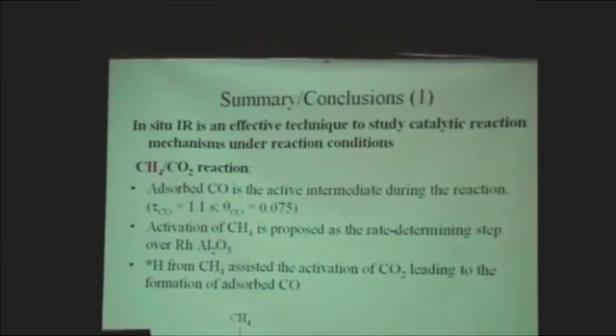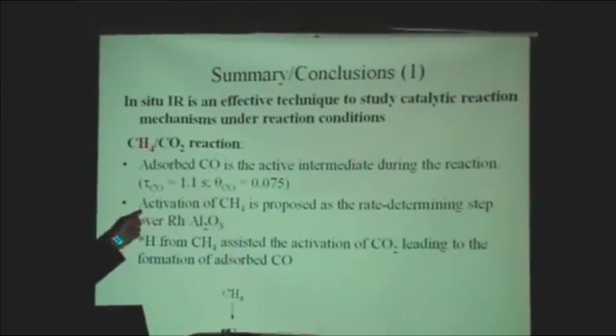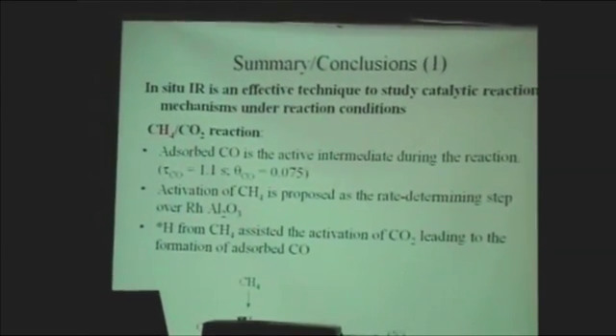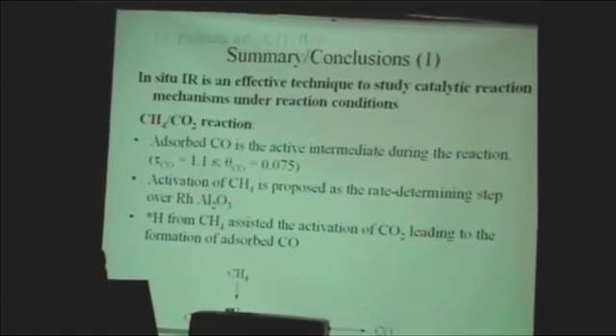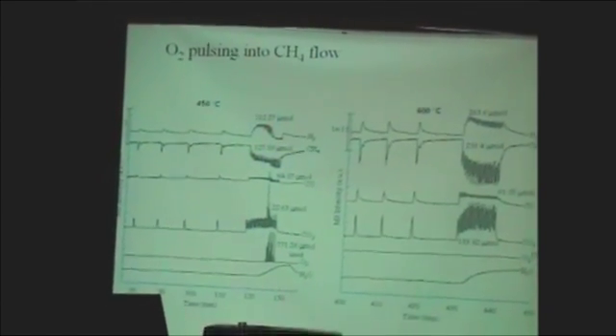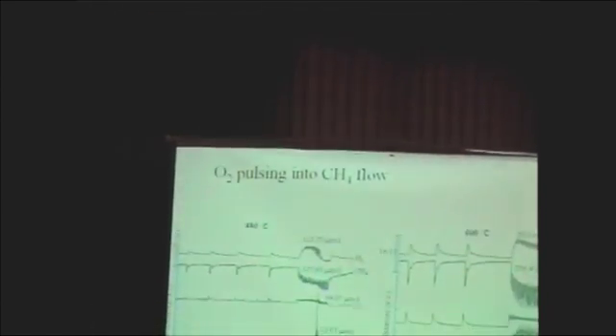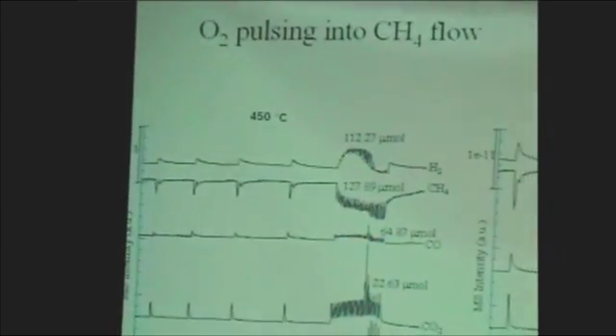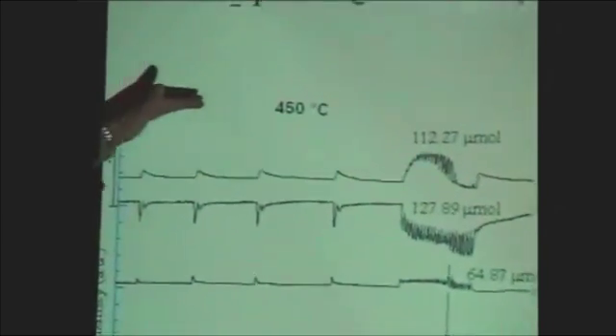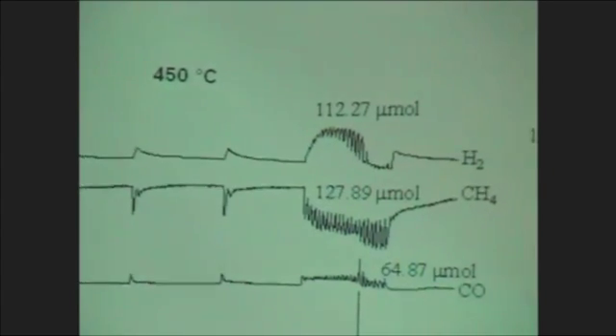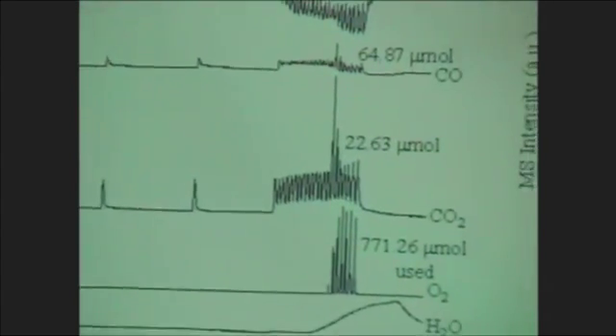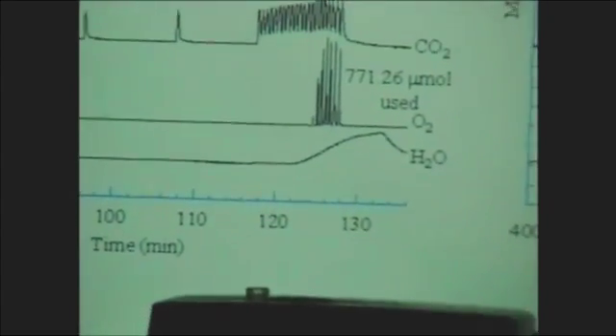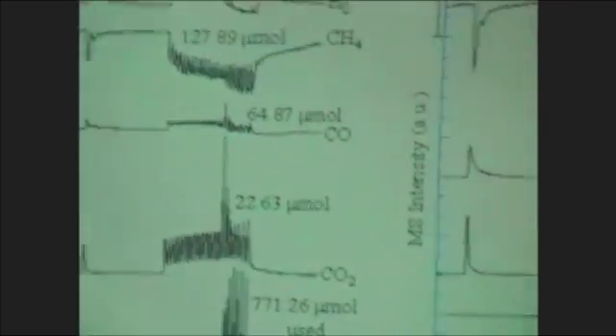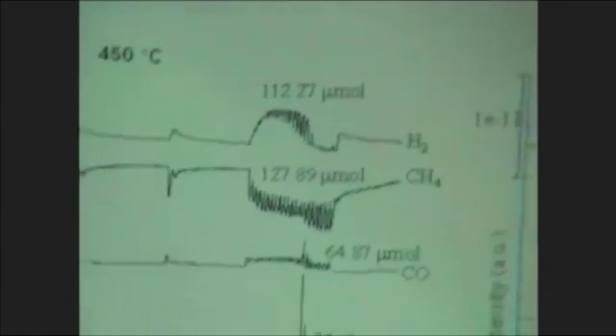So in order to figure out whether activation of methane is the rate determining step, we also tried to study the partial oxidation. I want to share the partial oxidation result with you. This is the result of partial oxidation we did here. Again, we sent about 30 cc per minute of methane flowing through the reactor. Then we pulse 1 cc of oxygen at 400 degrees and 450 degrees to 600 degrees C. Again, we make this oxygen pulse.